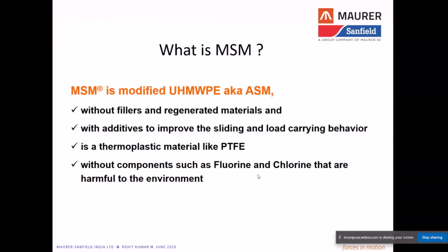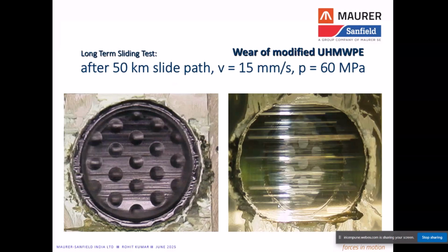So the research was started, and during this research a new modified material was manufactured. The generic name is UHMWPE, ultra high molecular weight polyethylene, without any filler or regenerative materials, and with some additives which improve the sliding and load carrying behavior. It is similar to thermoplastic material like PTFE, but without components such as fluorine and chlorine that are harmful for our environment.